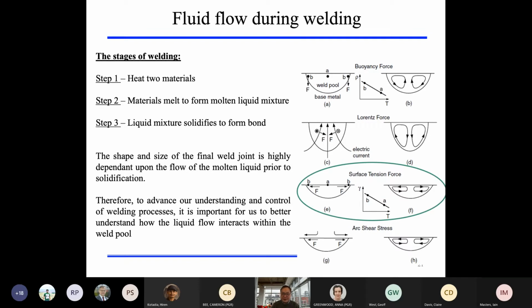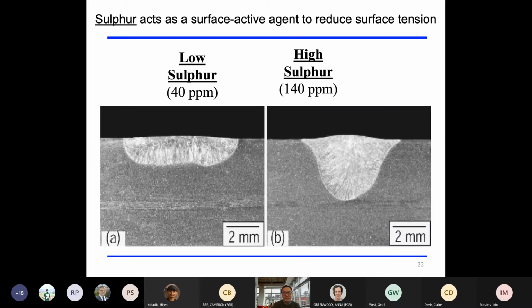So now in the next few slides, I will look into how this kind of surface tension change can modify the internal flow, and then modify the morphology of the weld pool shape. For example, this previous study says sulfur can act as a surface active agent to reduce the surface tension. When you have low sulfur and higher surface tension, you get very shallow pools. When you introduce this kind of sulfur surface active agent, you can deepen the pool and modify the morphology of the weld pool significantly, right?